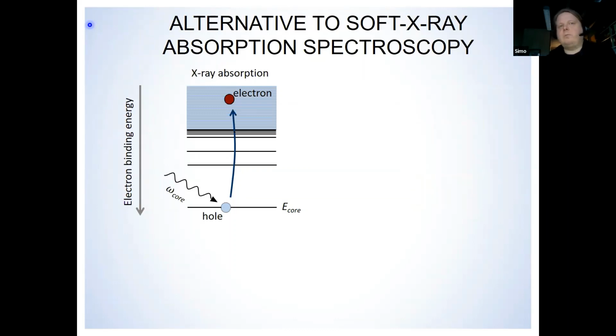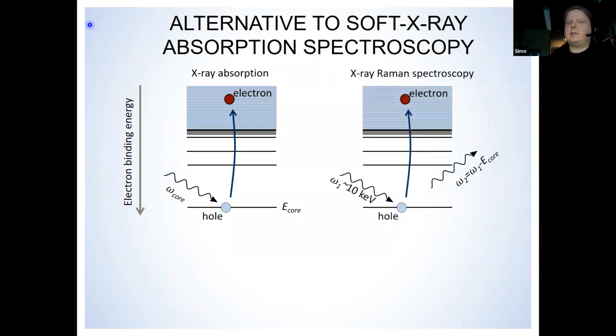What we do here is an alternative to soft X-ray absorption spectroscopy. In the XAS process, a photon interacts with the system and gets absorbed, and as a result an electron is promoted from an inner core shell to the unoccupied states, in the one-electron picture. What we do in inelastic scattering is that we come in with a photon that has much higher energy than the binding energy or the excitation energy of the electronic system. Nevertheless, it's still possible to create the same kind of excitation, and due to energy conservation, another photon must be created and emerge from the system with a smaller energy than the incoming photon energy.